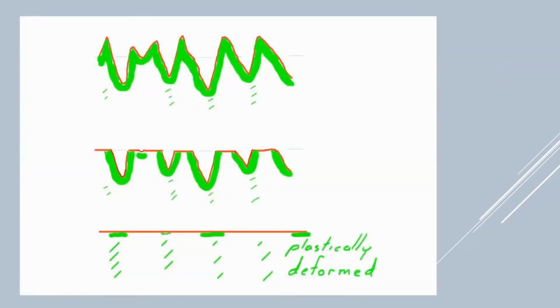And this is what happens: we're just looking at the side view, and underneath all those scratches is that green band that's been plastically deformed. If we don't take the scratches off and that green band, we end up getting that grinding damage that you saw in that previous one. So if we grind off all the scratches, there still are plastically deformed layers underneath, and we have to grind a little bit longer to get rid of that. But you're always under pressure to get things done quickly.